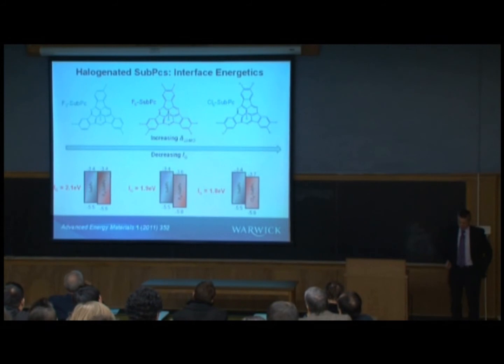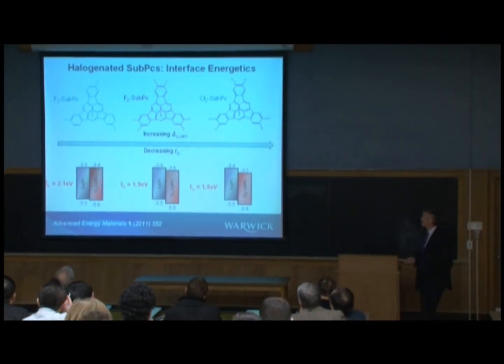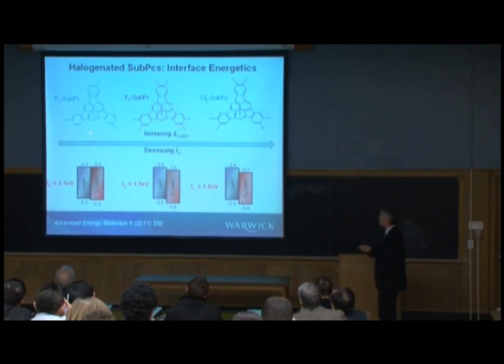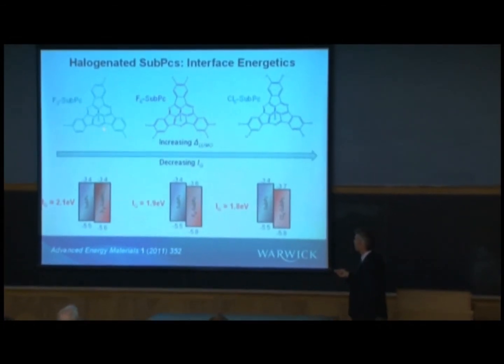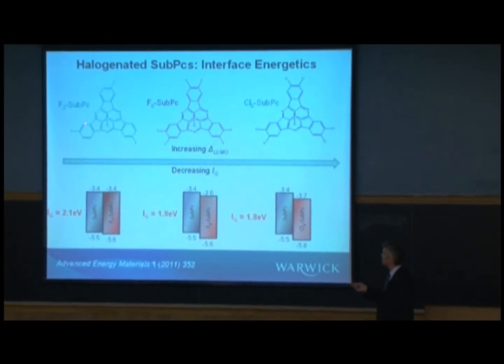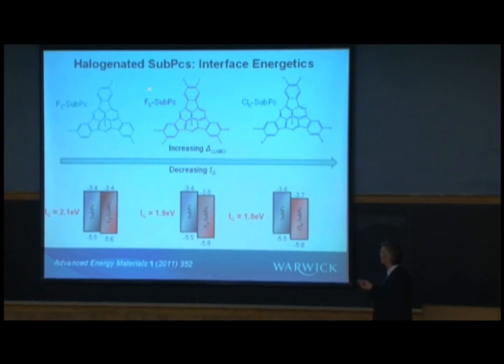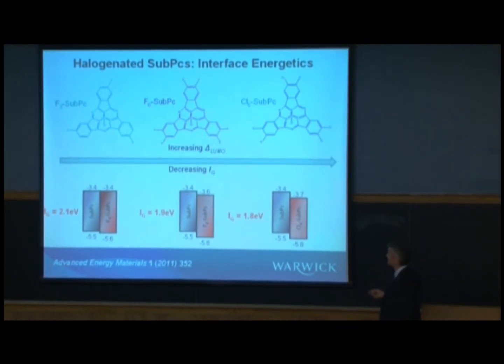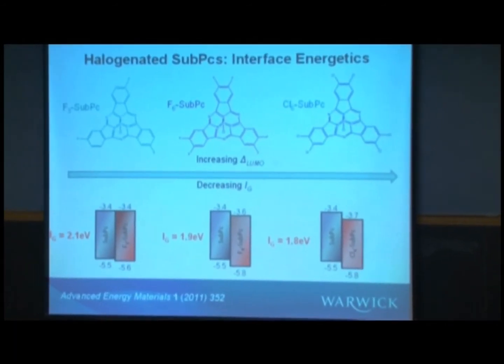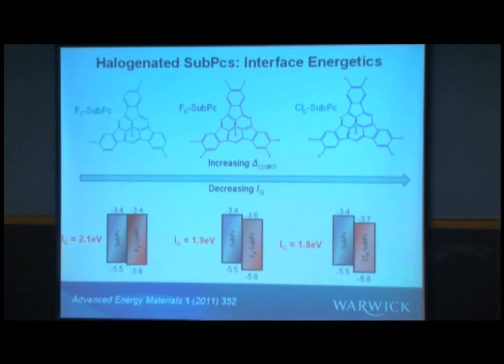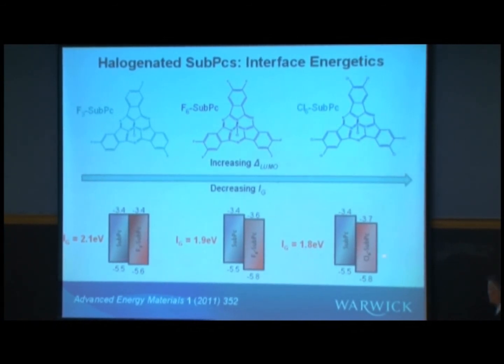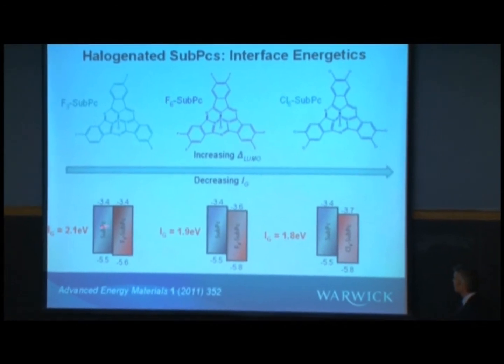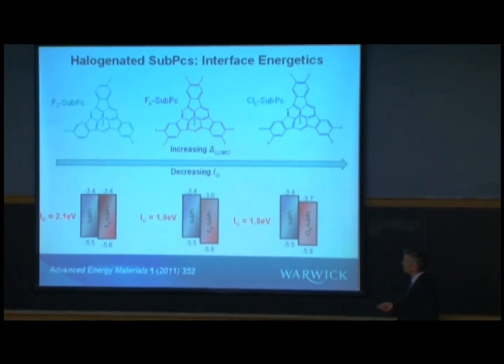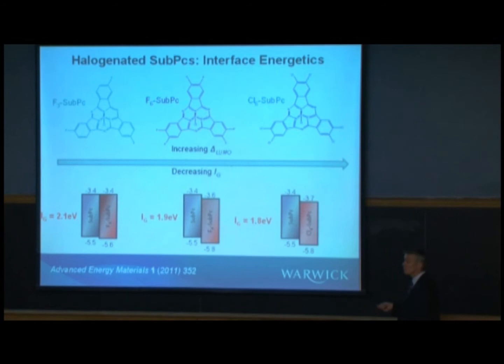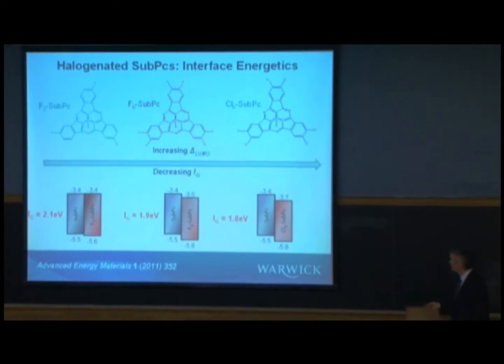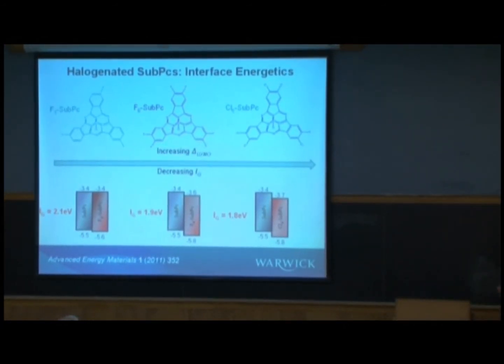These are three materials that a colleague of mine at Warwick, Mike Shipman, made. He made a family of subphthalocyanine, so it's taking the basic molecule, the trifluoro substituted, hexafluoro substituted, and a hexachloro substituted subphthalocyanine. Again, this is the energetics based on photoemission. As you go across this diagram, the interface gap goes from 2.1 eV, which is very large, down to 1.8 eV, which is still quite large.